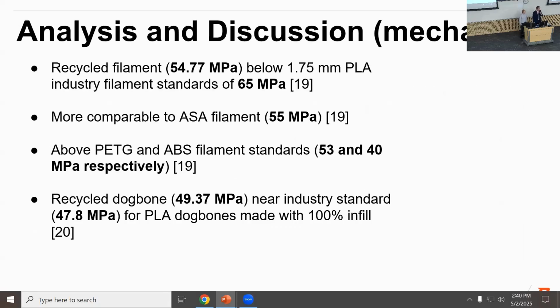With our filament, the recycled stuff that we made from the beer pints being around 55 megapascals, it was slightly below the industry standards of 1.75 millimeter PLA filament that is available for commercial purchase. This is usually at 65 megapascals, but our recycled filament could be used comparably with ASA filament and is stronger than PETG and ABS filament based on their standards for filament.